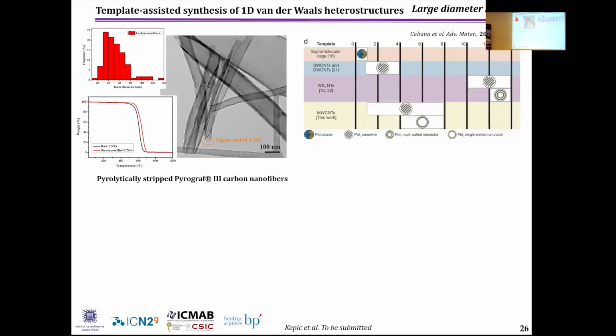So another problem or another issue is that there was like a threshold in the formation of nanotubes inside carbon nanotubes or inside tubular nanostructure. It was reported that only below 10 or 12 nanometers, single layer nanostructures are synthesized. And this is a problem because usually when you increase the number of layers, you also change the property of the material. So the synthesis of single layer systems is desired. That's why we evaluate the formation of this nanostructure inside carbon nanotubes.